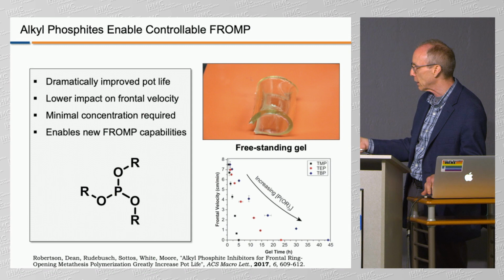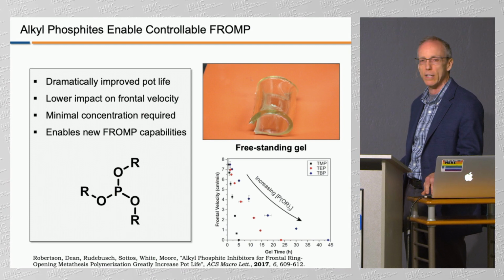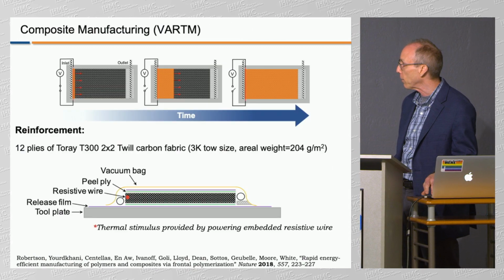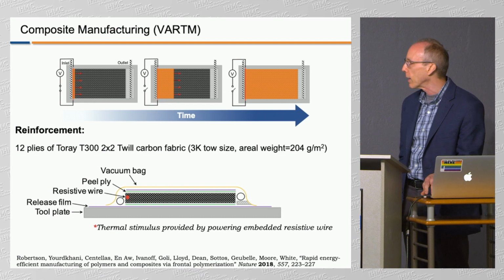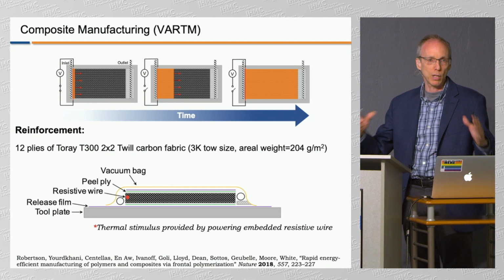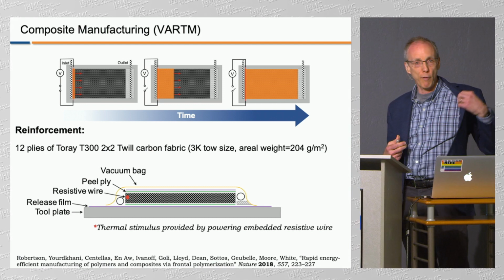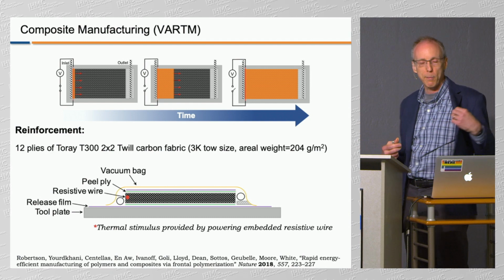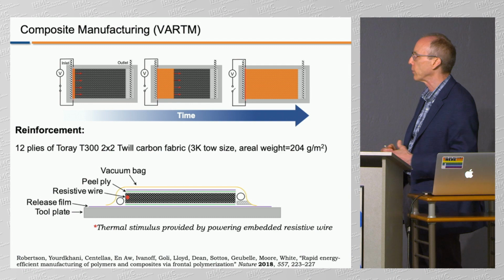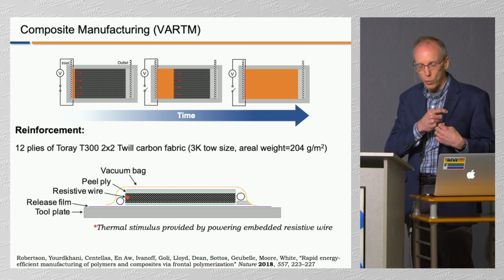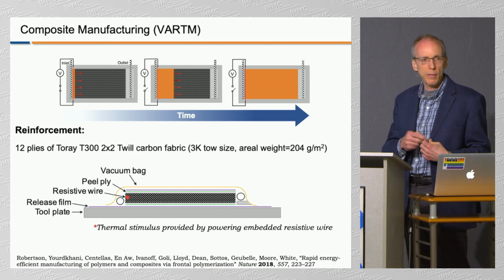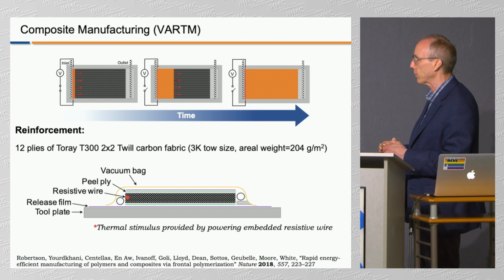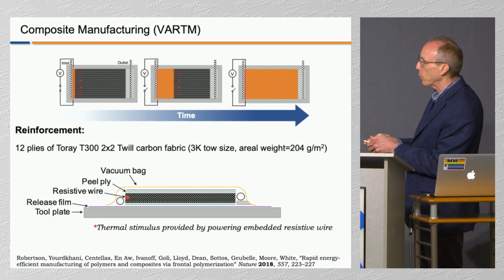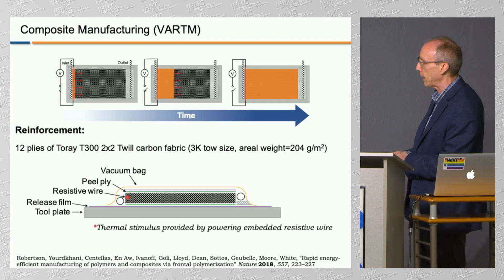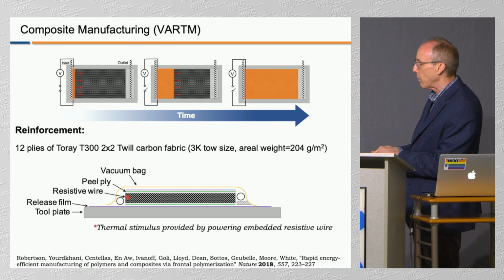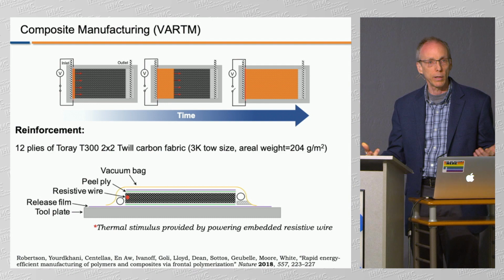And chemists like plots like this, but all I'll just say is we can control this reaction with great fidelity. And that allows us to do things like composite manufacturing. And so those composites that make the fuselage or the wind turbine are basically woven fabric, and that fabric is made out of carbon fibers, really stiff and strong, and then we would wick our liquid monomer into the fabric, and then we would ignite the frontal ring opening metathesis polymerization, at least in theory. So if we had a wire that was going to heat up, we'd get a traveling wave that would look something like that. And so this is kind of the side view of that. So we basically infiltrate or infuse in a lot of this liquid, and then we ignite it.